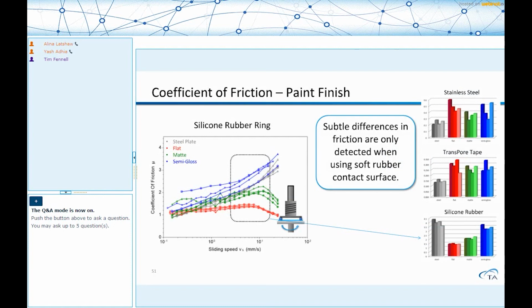The first point that I want to make is that the flat paint is on the much lower side, compared to matte and semi-gloss. Now, if you knew the exact composition of these materials and what was making it flat versus semi-gloss, we can, of course, delve into it, couple it with the rheological measurements, and understand what is happening. The other thing, from a practical standpoint, that I want to highlight is that between stainless steel and transport tape, if you look at the bar charts on the right hand side, metal at the bottom and the paint surface at the bottom. If that's your setup, and you try to make measurements with that setup, it actually starts showing differences. And that's mainly because the rubber is providing a lot more grip to start elucidating these subtle differences between the materials.